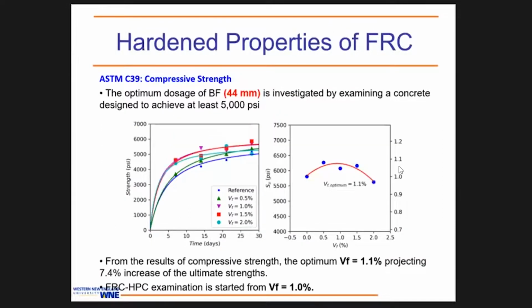Then we did our compressive strength test, C39, as you are already familiar with, with the 44 millimeter wires or mini bars. As you can see, the blue line is the reference line. We are targeting regular concrete of 5,000 to 6,000 PSI, and adding fibers, the 44 millimeter wires, the compressive strength increased a little bit, about 7%. The optimal volume of the fiber turns out to be 1% or 1.1%, but that is pretty much aligned with the steel fiber